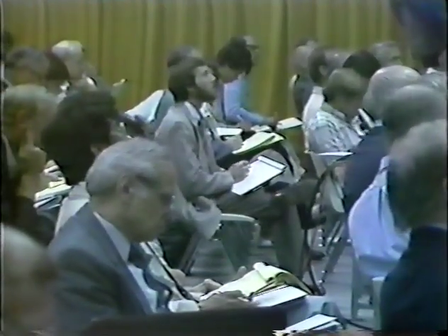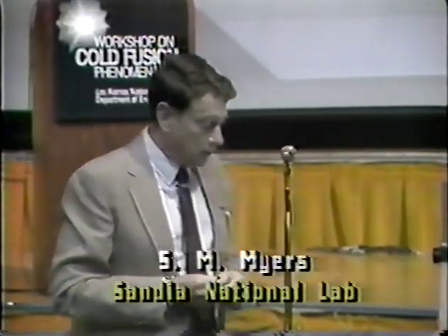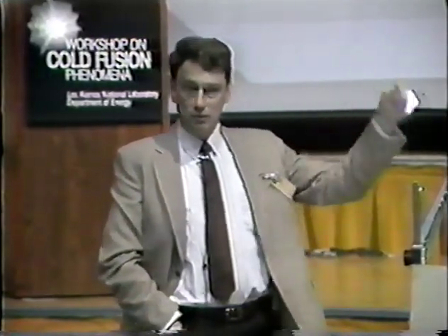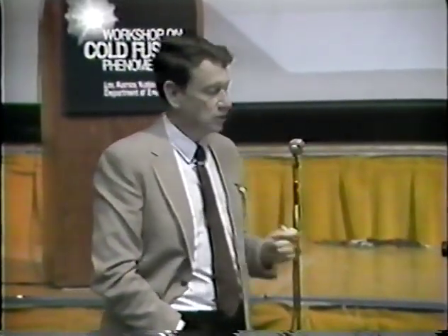The energetics of this kind of system were discussed by Pete Richards earlier this week. The essence of it is that in the normal deuteride, with the octahedral sites not fully populated, you have thermally activated diffusion in which you hop from the octahedral site over a saddle point to the tetrahedral site and then to another octahedral site. If, however, the octahedral sites are filled, the excess deuterium cannot drop into such low energy sites, and therefore the activation energy to get over the saddle point is less.